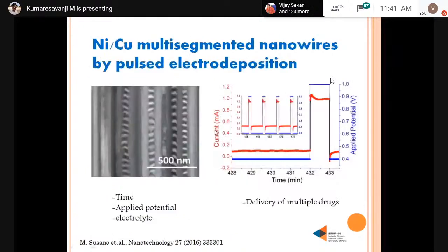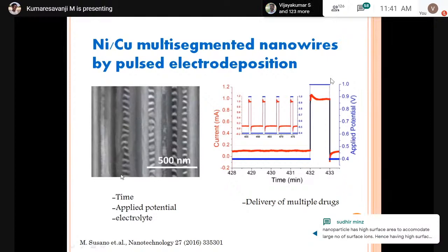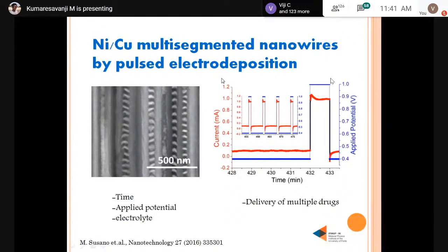Another interesting thing is the multi-segmented nanowires. Here I show nickel copper multi-segmented nanowires, like nickel copper, nickel copper, nickel copper. Such multi-segmented nanowires can be achieved by pulse electrodeposition. With the same method, we just pour two kinds of electrolytes, nickel and copper electrolytes. Then each one reacts at a different potential. For example, at 0.1 volts it reacts one material, whereas at 1 volt it reacts another material.